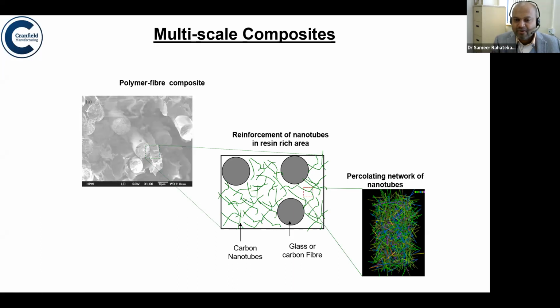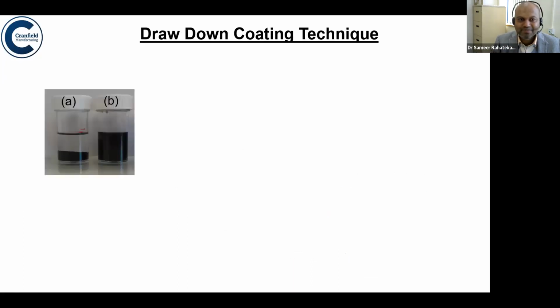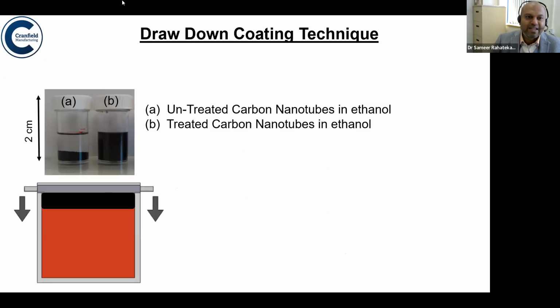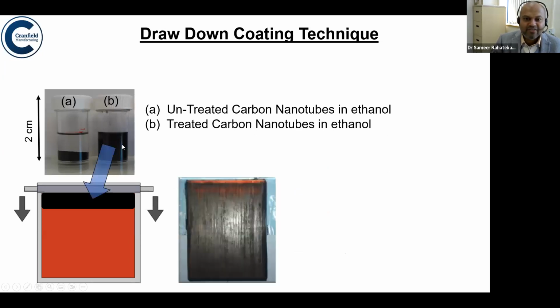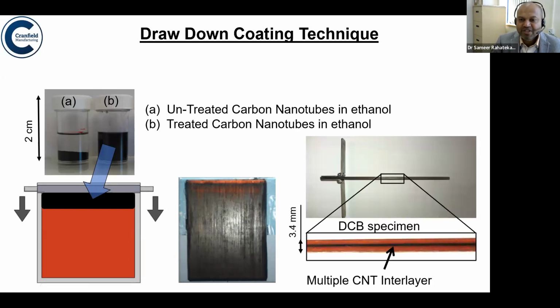We work quite a lot on it for last 10 years. So in future generation of composites, the crack propagation will be reduced if you were to use nanotechnology for aerospace applications. How do we do it? Very briefly, we take a suspension of carbon nanotubes in a simple solvent like ethanol, use that ink to coat a surface of, in this case, glass fiber composite. So original color here was this sort of red. And if you coat it with carbon nanotubes, it becomes black. And then we make a composite from it.